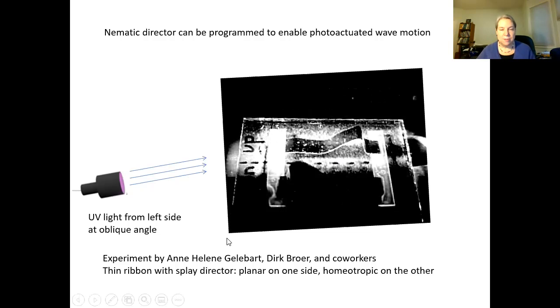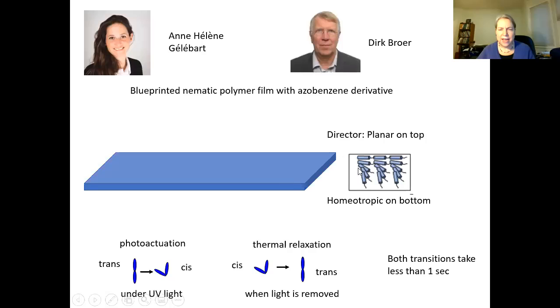Okay, so we need to know something about how they fabricated these films. What's the director? One side is planar, so the nematic director is parallel to the long axis of the film on one side. It's homeotropic, that is to say perpendicular, on the bottom, and in between it has a gentle splay. This is Anne-Helene Gellebar, and this is Dick Brower, her advisor.